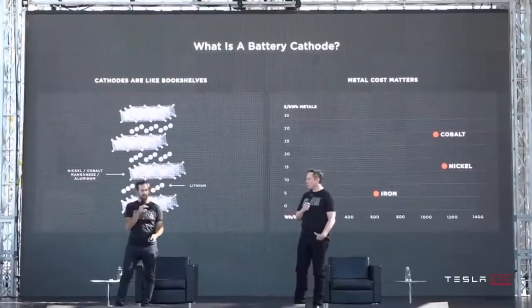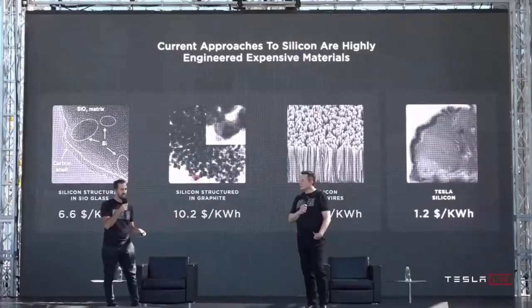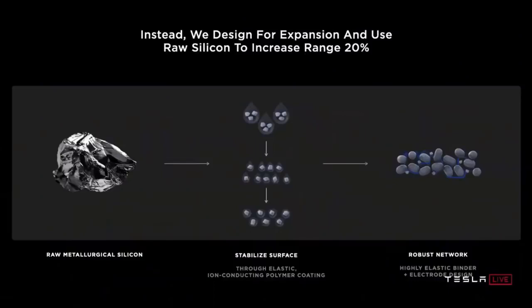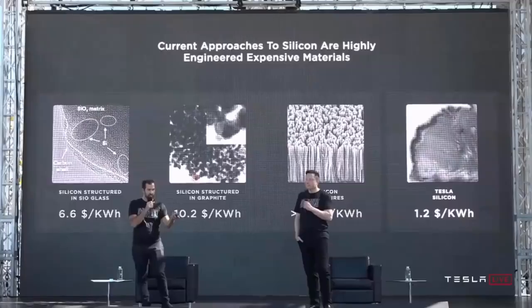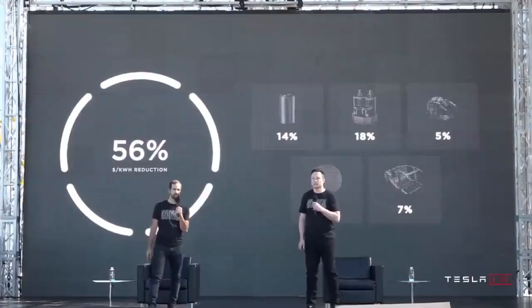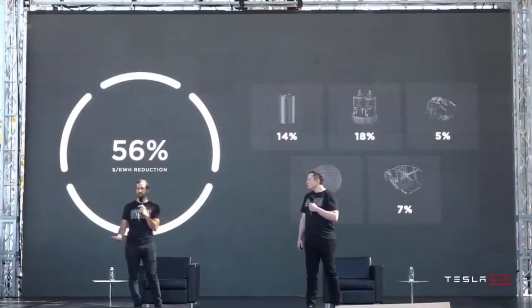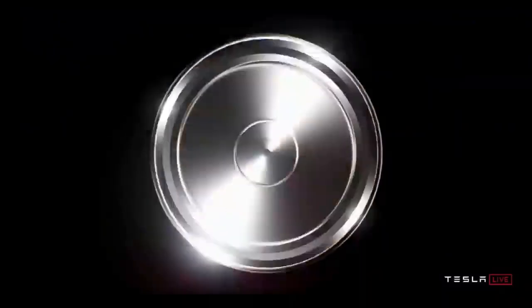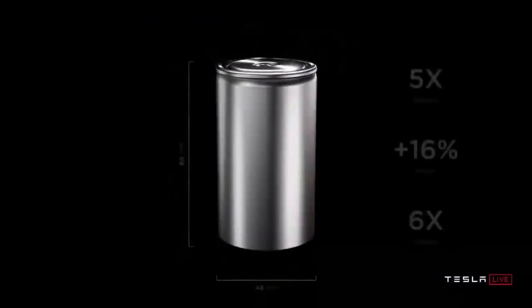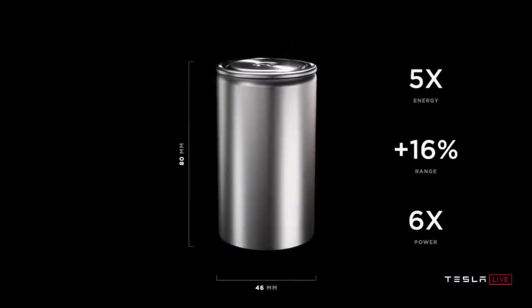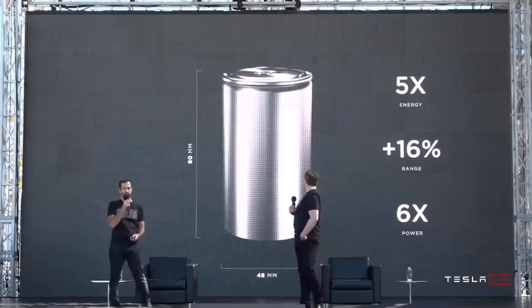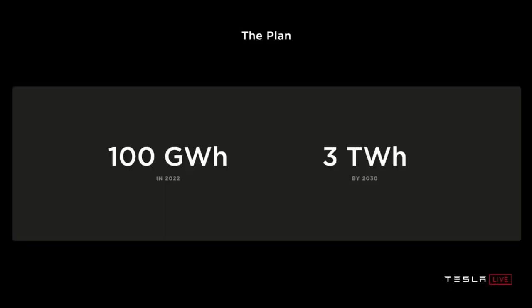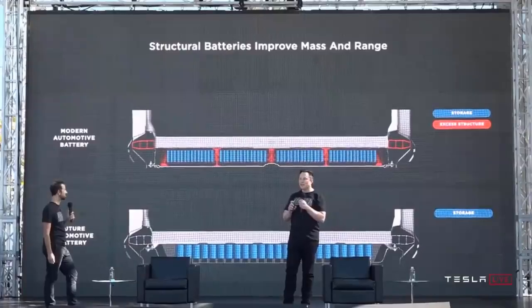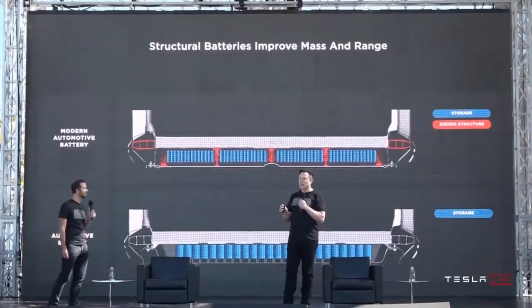Tesla also introduced high-nickel cathodes that eliminate the need for cobalt, and improved silicon battery chemistry in which they stabilize the surface with an elastic ion-conducting polymer coating that allows for a higher percentage of cheap commoditized silicon to be used in cell manufacture. Altogether, these changes create an expected 56% improvement in Tesla's cost per kilowatt-hour. And the new 4680 cells expect to achieve a 5 times increase in energy storage, a 16% increase in range, and a 6 times increase in power. Tesla hopes the improved cell design will allow them to achieve an eventual production target of 3 terawatt-hours per year by 2030 and help scale the world's transition to ubiquitous long-distance electric vehicles.